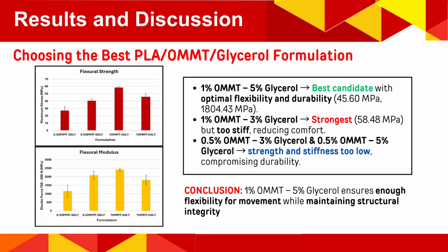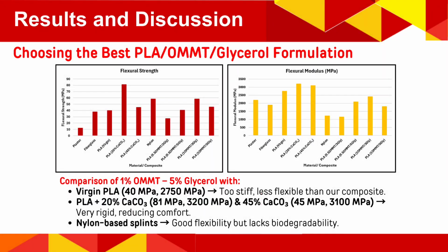applications. To further assess the suitability of our composite, we compared its flexural properties with those of conventional wrist splint materials. Our formulation exhibited higher flexural strength than virgin PLA and nylon, ensuring better load-bearing capacity. While PLA composites with calcium carbonate had higher stiffness, their rigidity could cause discomfort. Our material's balance of strength and flexibility makes it a promising alternative to conventional splinting materials.